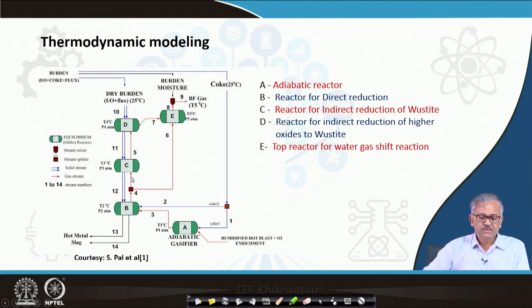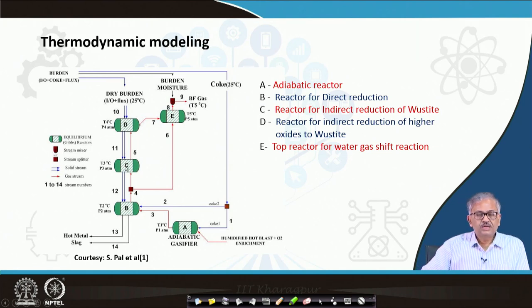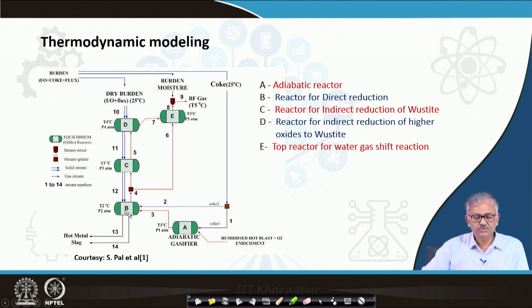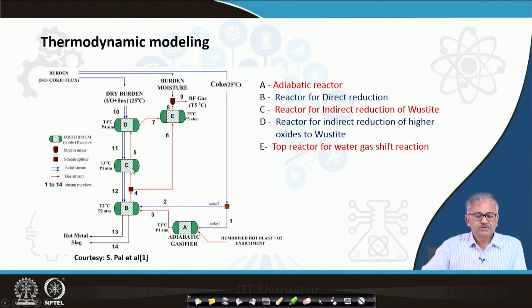This is reactor C where indirect reduction of wüstite takes place. From here the gas stream — the CO gas — is going, and the wüstite will come out along with the flux. The wüstite will be partially indirectly reduced and whatever wüstite is left out will come here and be finally directly reduced — or part may be indirectly reduced by the CO from the adiabatic reactor. This thermodynamic reactor will come to an equilibrium.